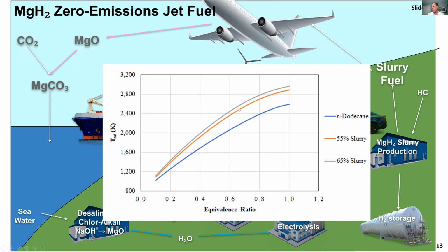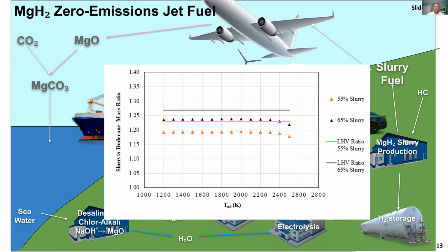Therefore, these jet engines generally burn lean, and an equivalence ratio less than 1 shows how much leaner. As you can see, slurries with high magnesium hydride loading burn at a higher adiabatic temperature because magnesium is a better energy carrier. What's important here is how much fuel is needed to reach a certain temperature, because that determines the thrust. So per unit mass, it takes a higher mass of this slurry, the 65% slurry corresponding to a 1-to-1 magnesium to carbon ratio than for your hydrocarbon.